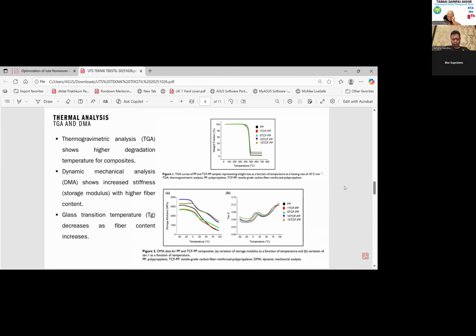The overall point here is that the TCF not only improves the stiffness and heat resistance, but also changes how the material behaves dynamically. So from the thermal point of view, the composite becomes more stable and better performing under heat and vibration. So a great advantage for sure for automotive and mechanical parts. Move on to the next slide.